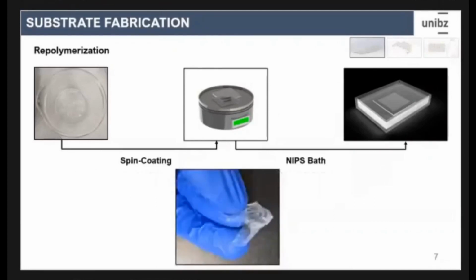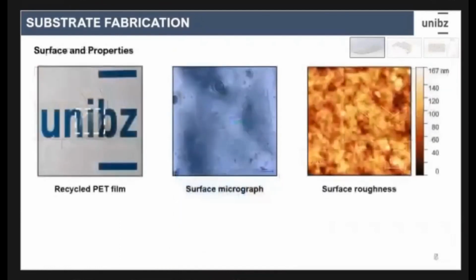Now, this is the result, a fairly transparent film, but one problem that we saw is that it has some wrinkles or warpage on the surface. This is because of the spin coating process: when you spin coat the polymerized polymer, the molecules don't align. And since you are kind of freezing it, the molecules are not aligned, creating this waviness on the surface. However, the waviness at the microscopic level didn't create a big problem for our purposes, since we can see here a very smooth surface with low roughness.